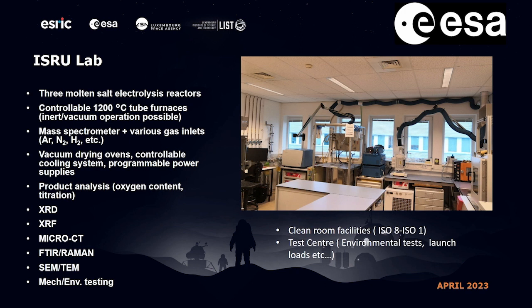We can provide information about the oxygen content by doing elemental analysis. We can do titration on the salts to look at the oxygen content or calcium oxide. We can do analysis using X-ray diffraction and fluorescence. We have micro-CT facilities as well, Raman, FTIR, SEM, TEM, and very dedicated mechanical testing, which is used by our colleagues in sister sections. So tensile strength, compressive strength testing, microindentation, all these facilities are there and available.